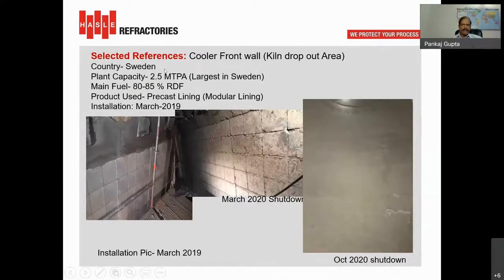This is a case from Sweden, which is using 80 to 85% RDF, and it is installed in the cooler front wall just below the discharge end of the kiln. We installed it here in March 2019, and this is the picture after 1.5 years. The modular lining is still intact without any issue.